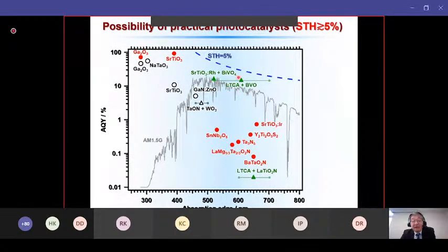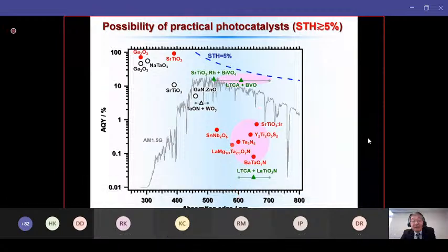However, to achieve the STH value of 5%, we have to get into this region. At present, we have not yet gotten into this region. To reach this region, probably we need to improve the efficiency of these materials. I mean that the absorption edge is located at about 600 nanometers or even longer. So the question is, is it really possible to get into this region?